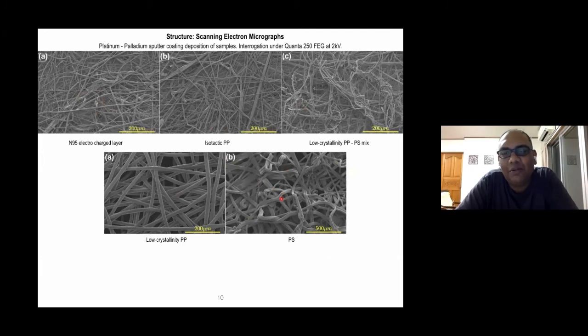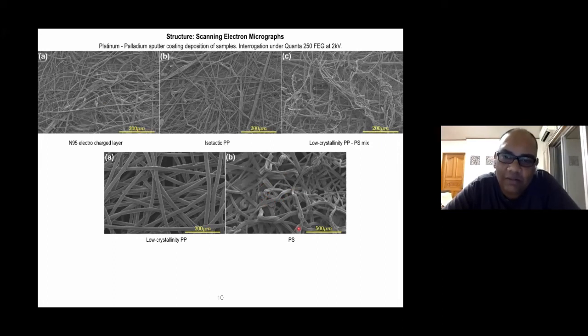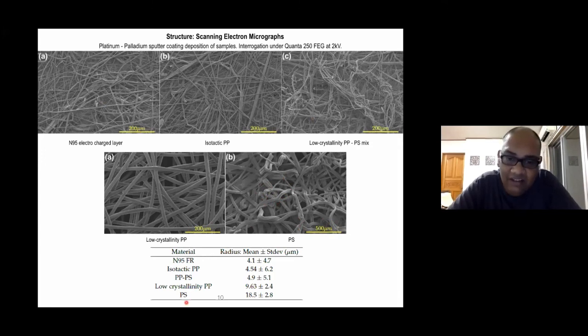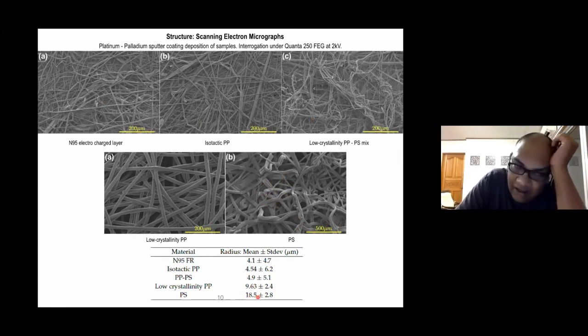Yes, but I could not get down to smaller diameters. You notice the scale bar. For all these images it is 200 microns, but for this it is 500 microns. These diameters are much higher. I was getting 18.5 micron fiber radius, not diameter, radius. I couldn't figure out a way to go down. The reason I realized in the last 2 days is that polypropylene is quite agnostic to changes in viscosity, surface tension, etc. above its melting temperature.